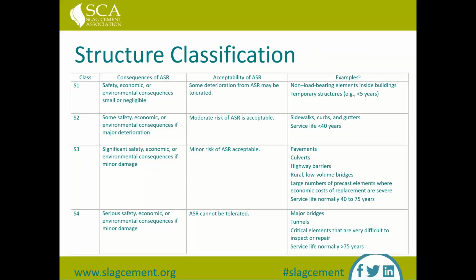Our next step is the structure classification. This classification comes from the consequences of ASR and the acceptability of ASR, and goes from an S1 to an S4 class, with S1 being that some deterioration may be tolerated, up to S4 where ASR cannot be tolerated. The documents give different examples for each class. An S1 might be a temporary structure. S2 would be sidewalks, curbs, and gutters. S3 would be pavements and rural bridges. Up to S4, the most severe classification, being major bridges and tunnels where you're expecting a service life over 75 to 100 years—your most severe structures.